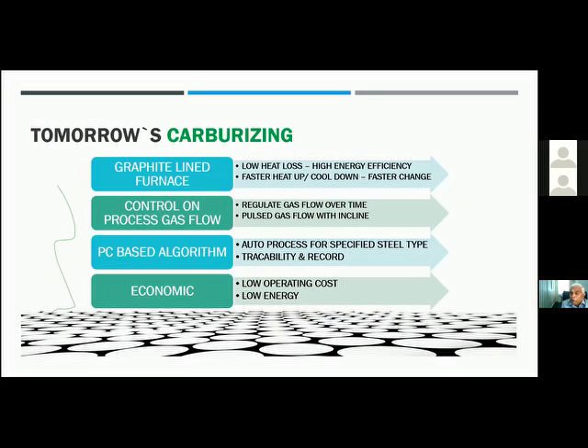The gas flows are pretty well regulated. I'm sure today's CGCs and IQFs also have these regulation capabilities, but the vacuum furnaces demand them because we're dealing with small flows of acetylene gas. And the flow of gas here is an extremely different kind of flow rather than a motorized valve or a solenoid valve flow. These are all pulse flow, and I'll make a sketch of this and show you how this pulse flow works. It's a pulse flow with an incline, where you can adjust the amplitude of the flow, the frequency of the flow, and the incline of the flow. And it's a very interesting concept, which makes a huge difference in preventing sooting and excess carbon deposition on the surface of the component.